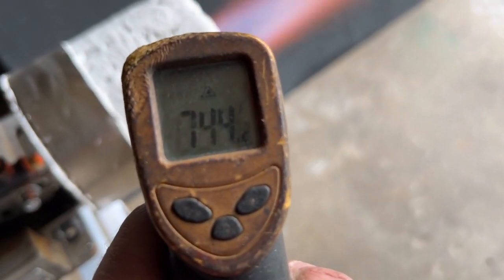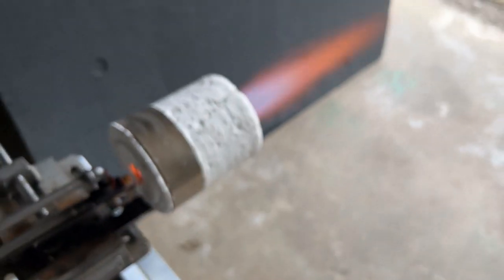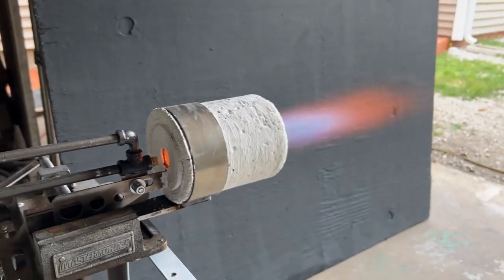Now I cast this combustion chamber quite some time ago and I had too much going on to pay attention to it and I let it crack. It dried too quickly, I didn't leave it wet while it was curing.